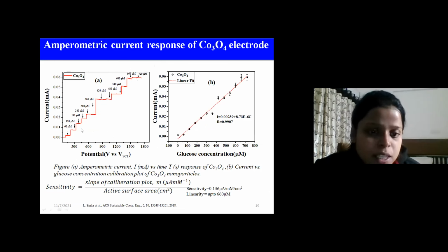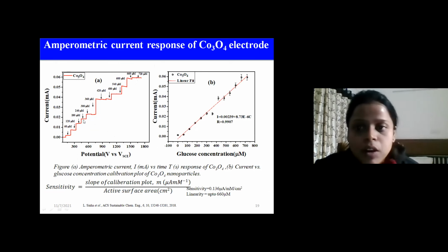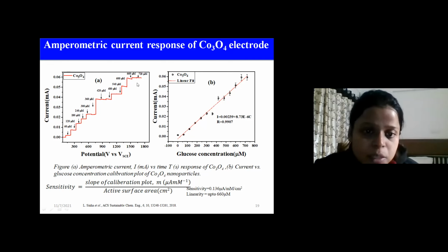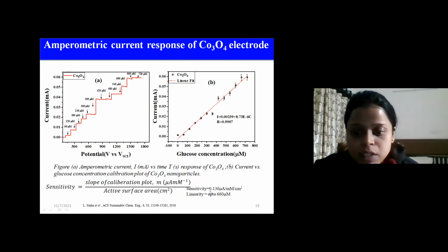And here we are seeing that by continuously, successively adding 60 micromolar of glucose. First we have done it for Co3O4 electrodes, just to compare the results. And here we are seeing that the material is giving a continuous enhancement in the current. So the sensitivity is calculated as 0.136 microampere per millimolar per centimeter square, and the linearity has been maintained up to 720 micromolar.